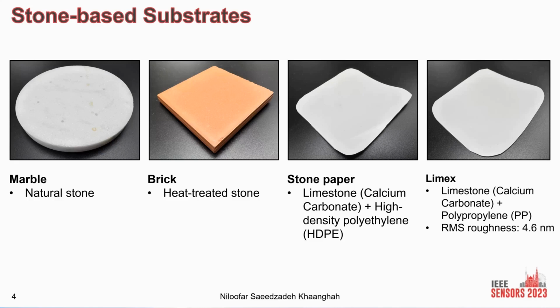I have the stone paper and the Limex, which are based on polymer and stone powder. The stone powder used in these two materials is limestone, or calcium carbonate, but the difference is in the binding agent. For stone paper, it is high-density polyethylene, and for the Limex, it's polypropylene. The root mean square roughness for the Limex is 4.6 nanometer, but the other substrate materials were too rough for AFM measurement. The stone paper and the Limex are commercially available and are good alternatives for conventional paper and plastics.